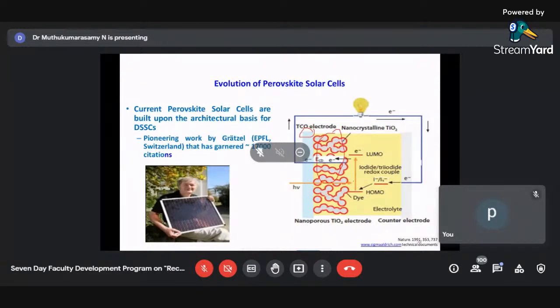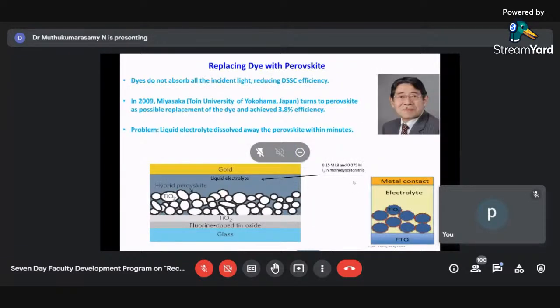So this is the dye-sensitized solar cell, and this was started by Gratzel, and people started to work with dye-sensitized solar cells, and they have reached an efficiency of 12%, 11% as of now. So this was the starting point for your perovskite solar cell. Now this dye which is there in the dye-sensitized solar cell was replaced by a perovskite material by Miyasaka in 2009, and he was able to produce an efficiency of 3.8%. You can see here what Miyasaka did was he introduced perovskite with your titanium dioxide. He mixed perovskite material with titanium dioxide, and he didn't use any dye, and he fabricated a solar cell. So he replaced the dye material with a perovskite material, fabricated a solar cell, and obtained an efficiency of 3.8%.